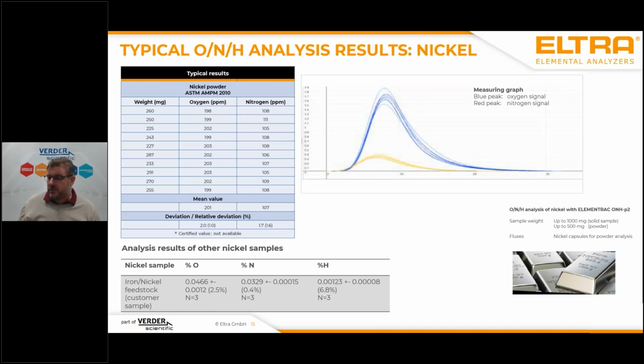And here again, we have processed an iron nickel feedstock sample, which came from a customer. And there you see that we get typical results of 0.05% of oxygen and 0.03% of nitrogen, and approximately 12 ppm of hydrogen. Hydrogen is done in a different measurement because in the ONH analyzer we have on the one hand a measuring mode for oxygen and nitrogen and on the other a measurement mode for hydrogen. This is also related to some regulations which are fixed in some ASTM standards. And as you can see here, like carbon sulfur analysis, oxygen and nitrogen analysis can be very, very precise, and is very easy for all kinds of samples and all kinds of, I would say, sample shapes.